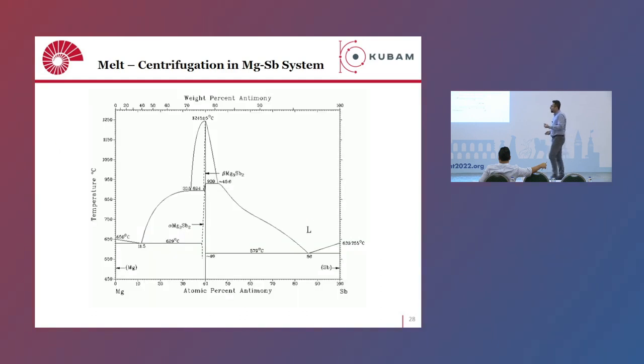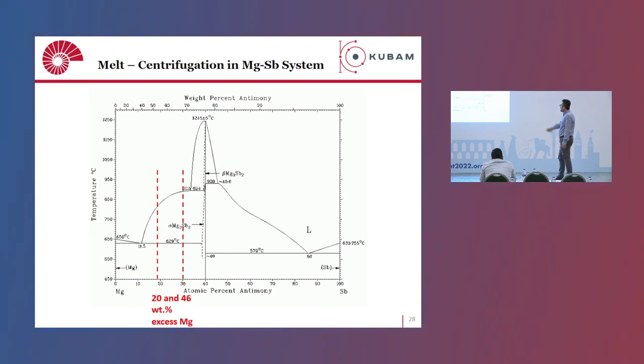Why? Because the nature is similar. Here you can see this is magnesium 3 antimony 2. Here we have magnesium, and between magnesium and magnesium 3 antimony 2, we also see such a eutectic temperature. So we went a little bit higher than 650, maybe 750, by adding excess magnesium and applied this technique. We added 20 and 46 weight % excess magnesium, and then did some research to see the effect of it. This is done in situ and by external addition.